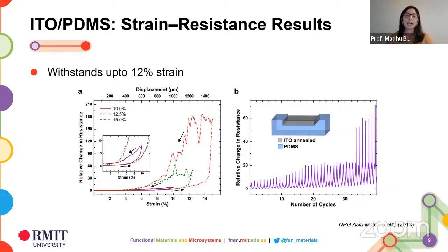And we were wondering now what happens if we actually apply strain on these materials. Now, typically an oxide layer is not going to withstand anything more than say 2 or 3% of strain. You would not really see much performance beyond that. So we were quite surprised when we could stretch these to up to around 12 or 15% and still manage to get some performance out of them. Beyond a particular percentage, like 15%, they become open circuit, which is why you don't really see much performance. But then once you bring it back to 0% of strain, you are able to keep using these devices. So this was really early stage measurements.